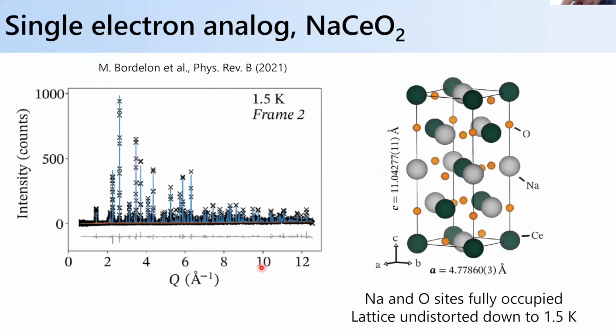So, to test the model further, we also decided to look at the single electron version, sodium cerium O2. And just as a prelude, the cerium version is the boring version of the two. Okay, so we did the powder neutron diffraction. Again, the sodium and oxygen sites are fully occupied. That's important for this material as well because it's not very air stable. And the lattice remains what we think it is, down to 1.5 Kelvin.